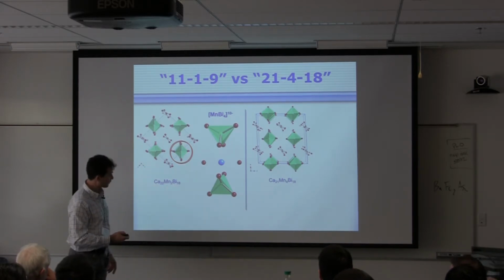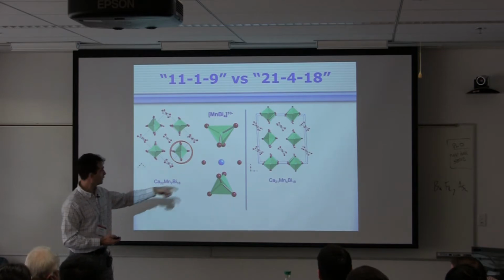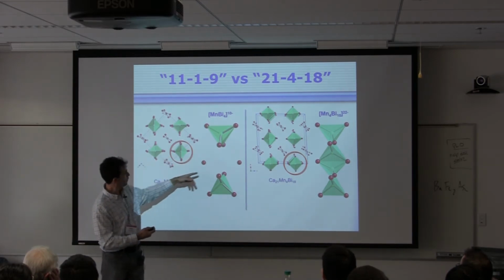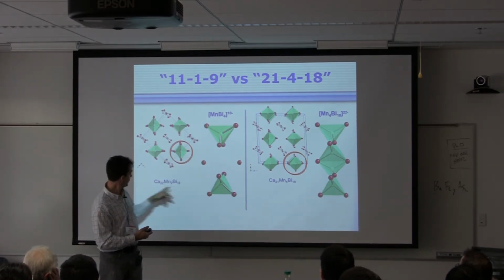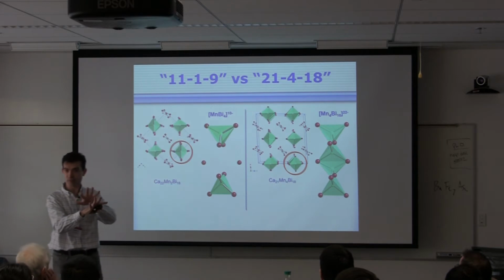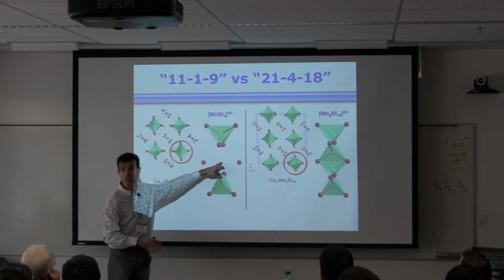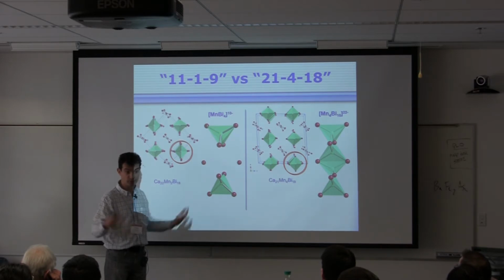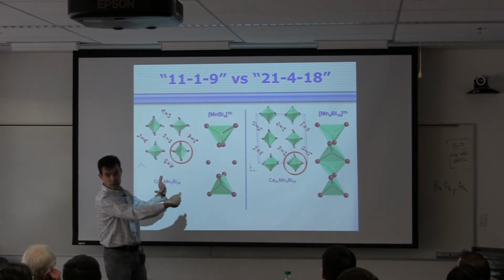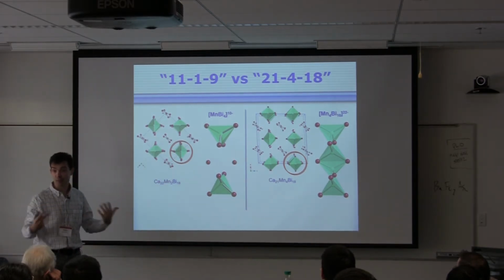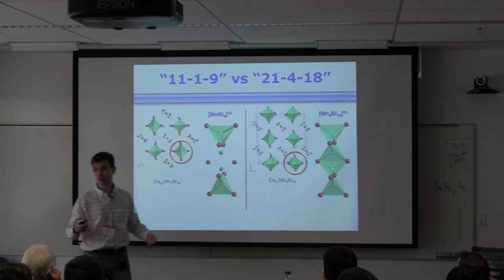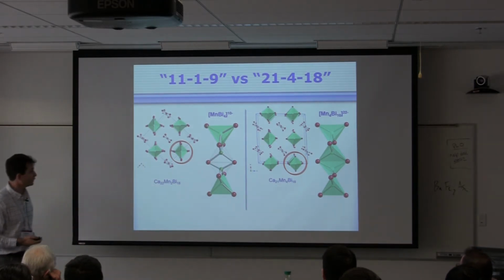22 to 18. If I take now with Photoshop the magic wand and I erase this, this is the arrangement in the actual structure. If I now take the magic wand in Photoshop and I fix 22 to 21, I'm getting closer, but still no cigar. So what happens now is I create a hole. Nature doesn't like holes. This is a close-packed structure, so those neighboring free antimonies come closer together to fill that hole. By doing that, you create two tetrahedral holes, which you can fill with two manganese. And then with Photoshop, you draw the bonds. Voila.